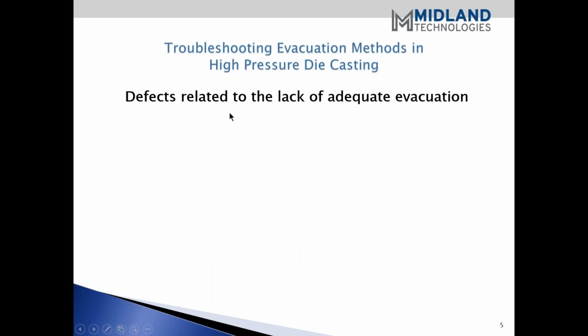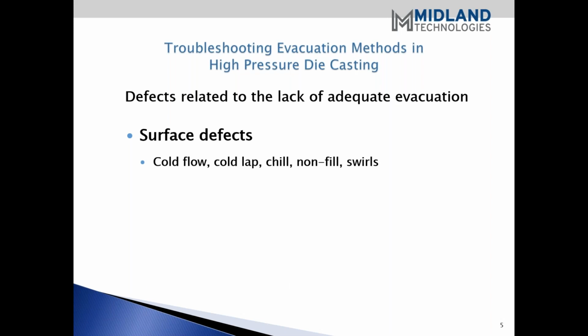So our first thing, look at what defects are related to the lack of adequate evacuation. And of course, the first part is surface defects, and cold flow, cold lap, chill, non-fill, and swirls. Larry, can you go over a little bit more description on that? Sure. These defects are related to evacuation of the cavity. They can also be influenced by the amount of time it takes to fill the cavity, in other words, the cavity fill time, and also the temperatures involving the metal or the temperature of the tool itself when the metal enters it.